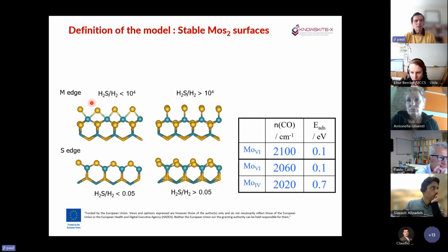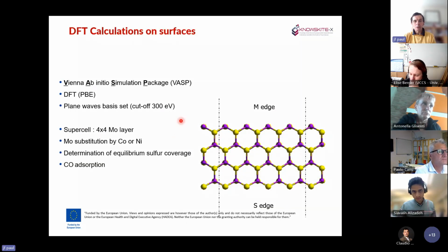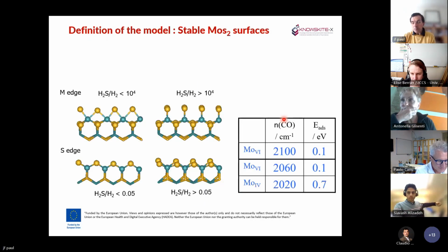And if we take into account the effect of the chemical potential of sulfur and hydrogen, we have shown that the molybdenum atoms on the edge are not alone, and you always have one or two sulfur atoms that are adsorbed on this atom. And for the other type of edge that you can create, you have a molybdenum atom here, and the coordination here is 4, and here the coordination is 6. And none of the surfaces is equivalent to what you can just build by cutting your crystal. You always have a lot of reconstruction, a lot of adsorption, and that will depend on the experimental conditions.